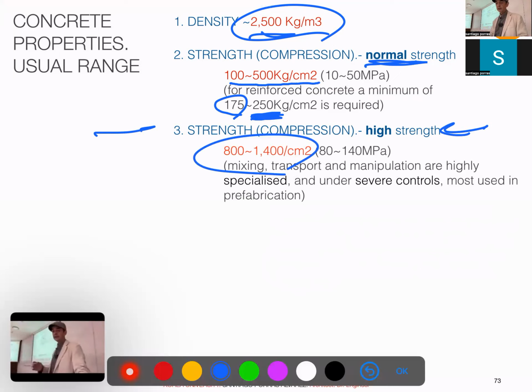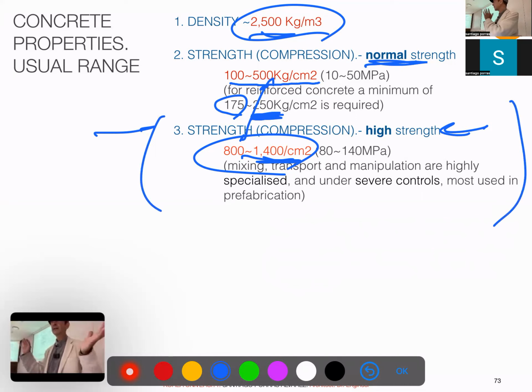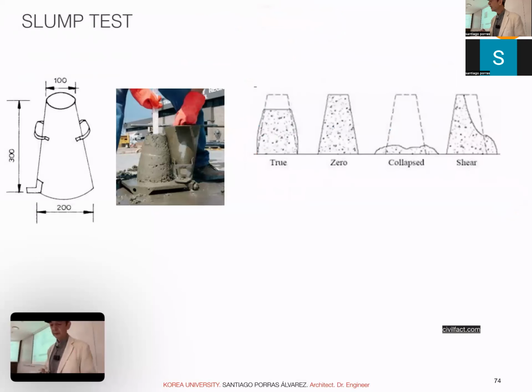And then the high strength goes much, much higher, right? There is a space between 500 and 800, an ambiguous area. If you go to the pain of adding a lot of cement, you get much more strength, but you will always need special laboratory work and really specialized workers. And this is what you see in the columns of high-rise towers of 50, 60 floors, because with this strength, it becomes competitive with steel. But this is very specialized. I personally have seen it, but I have never used it. But I have an idea of the problems there.